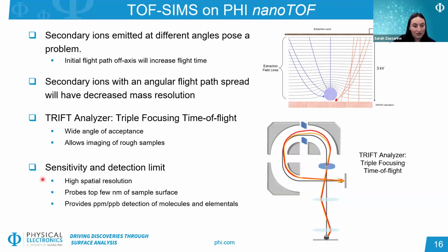And the TOF-SIMS technique generally has a very high spatial resolution as well as really nice detection limits on the ppm to ppb scale. So the ability to analyze these rough samples with all of these benefits is very suitable for this type of nanowire structure.